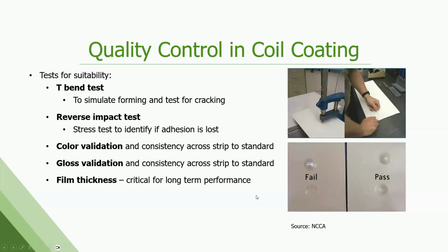So quality control, we do a lot of quality control. The paint companies do a lot of quality control in the paint before it even gets to us. And then once we apply it, cure it, bake it on, we do a lot more testing. So the really important things are we've got to simulate that forming and fabrication process it's going to go through. So we bend it, we bump it, we deform it. We check to make sure that paint is sticking and there's no loss of paint. We look at color, which is hugely important in this architectural space, consistently.